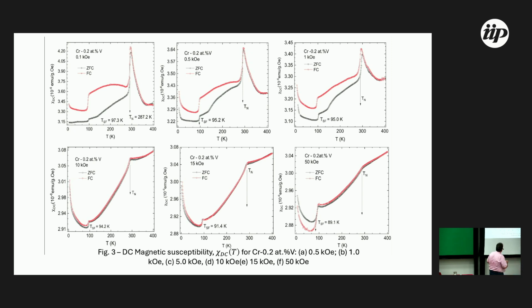Yeah? And when cooling down the sample, the local magnetic moment is frozen in the lattice, and the change of the magnetic order shows in this behavior. It is the opposite of the antiferromagnetic behavior in this case. In this case, local moments do not exist, because local moments appear only with the spin density wave. However, when I cool down the sample, the freezing of the local spin density wave around the vanadium atoms is my hypothesis. Okay?